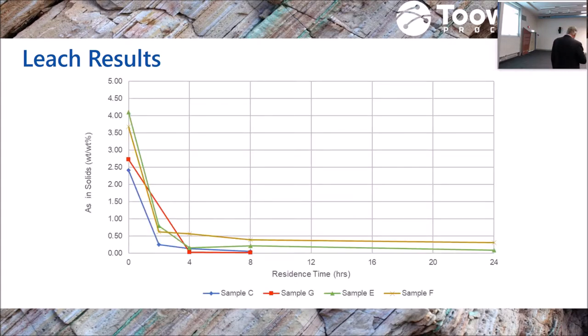One of the other things in the chemistry is the kinetics of the leaching. When you've got high arsenic concentrates or high antimony concentrates, the kinetics is very fast in the leaching stage. So it's a high density leach, it's sort of fast kinetics, so you're not having large residence times in the leach.